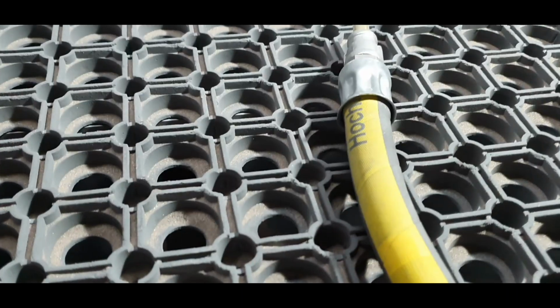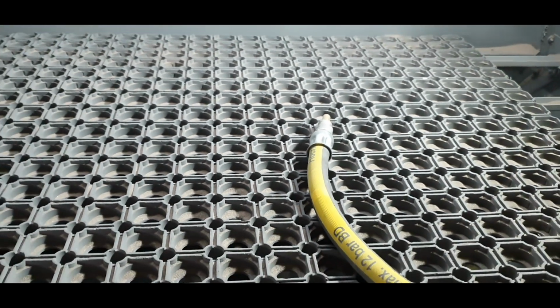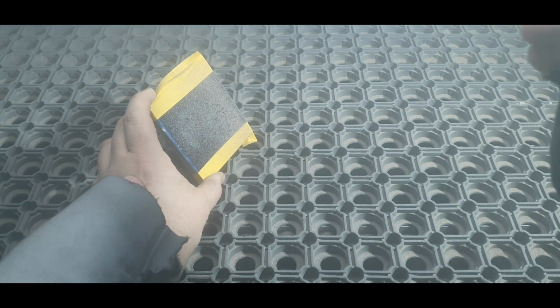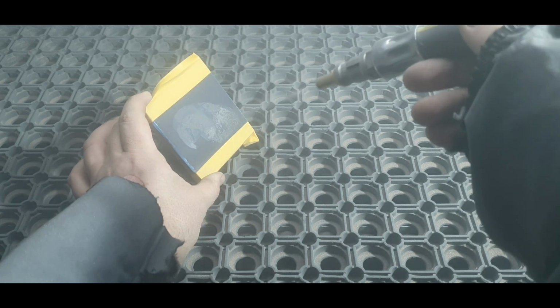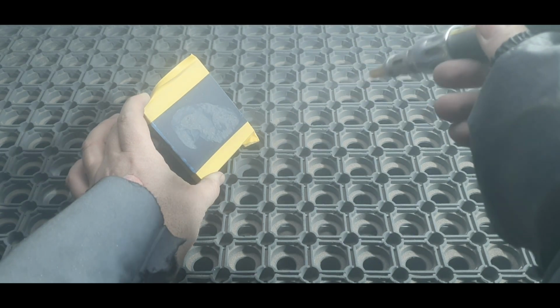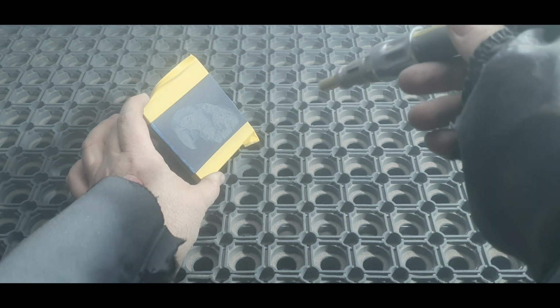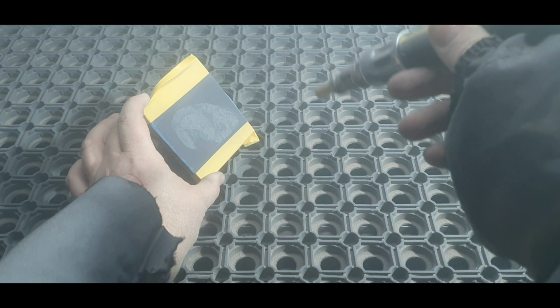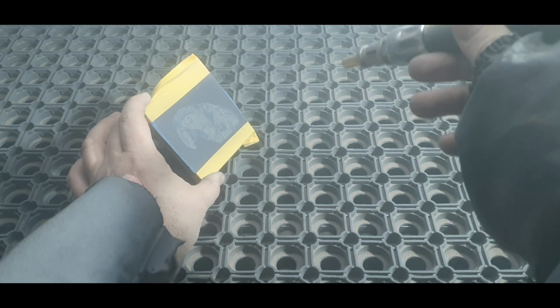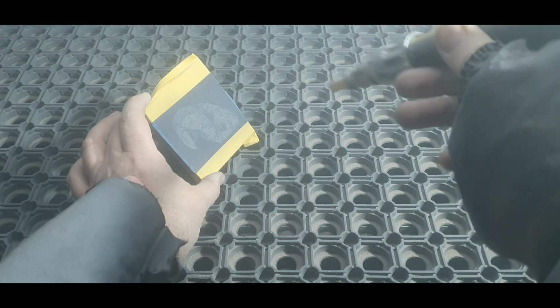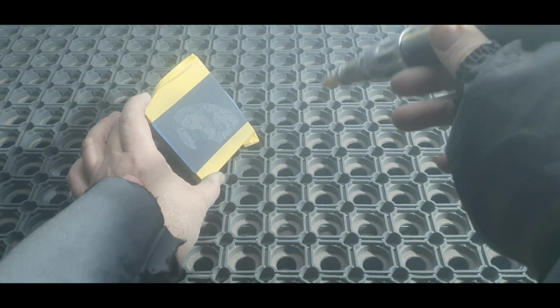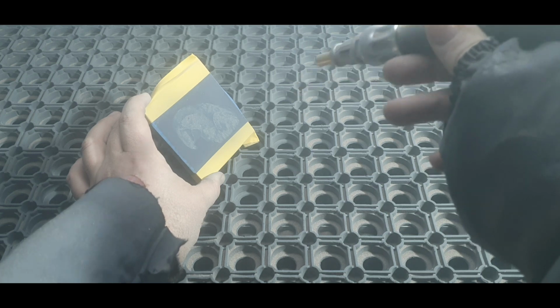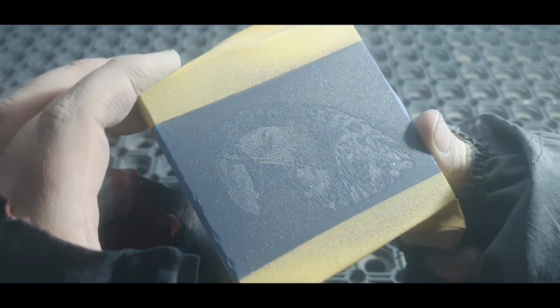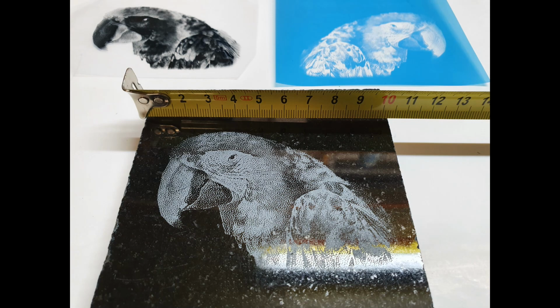Yeah, and here we have the carbide tip. So it's a boron carbide, 3.2 millimeter. I'm using aluminum oxide, 150 mesh, and let's say 29 psi. So 2 bar, not more. So, and sandblasting, it's the same way like airbrushing. You have to go line by line, very accurate. And that's it. It's no magic. But you have to have some skills and practice for sure. So that's it. So that's a colored engraved granite.